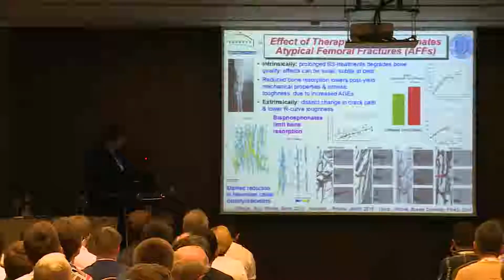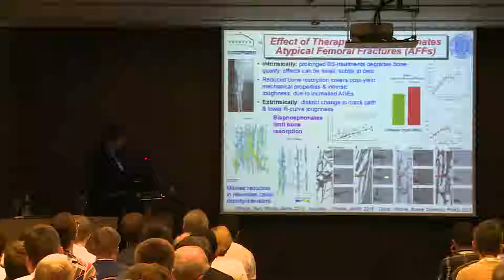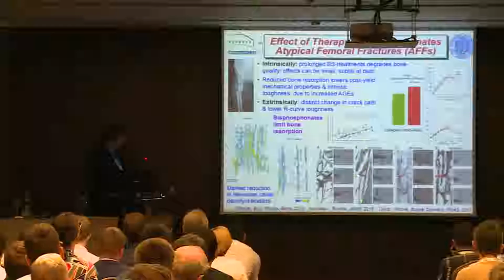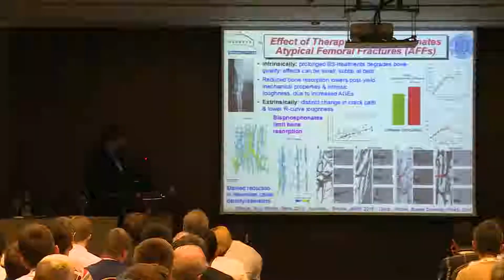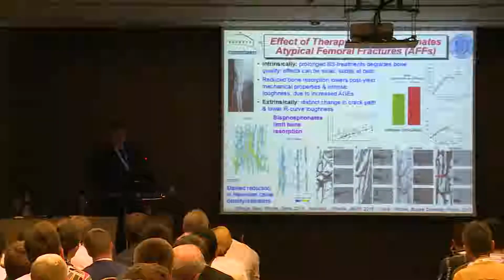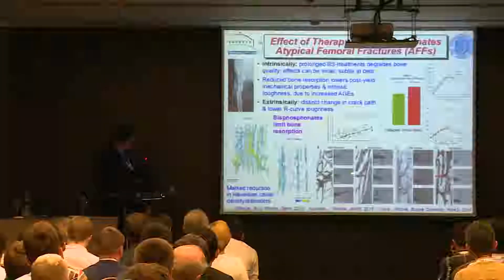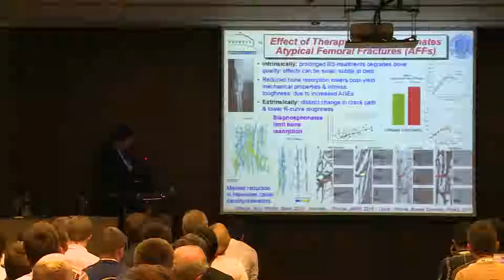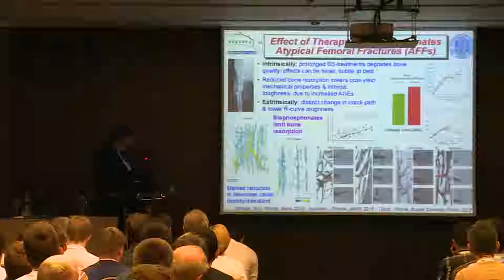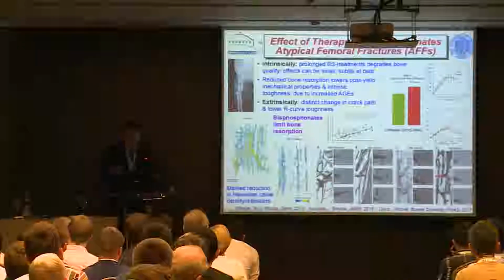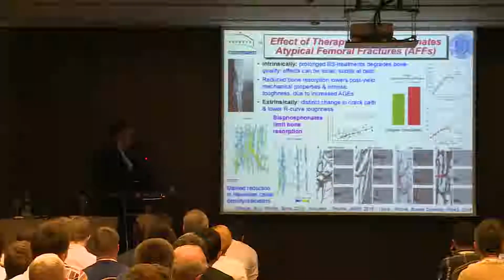Regular bone, you get the deflection. You see a crack's growing this way, the osteons are this way, and you see the crack tends to deflect. This is a very common thing you see in healthy bone, but in these people who are prone to this problem, the cracks just simply don't deflect. So there's something associated with an abnormal mineralization.